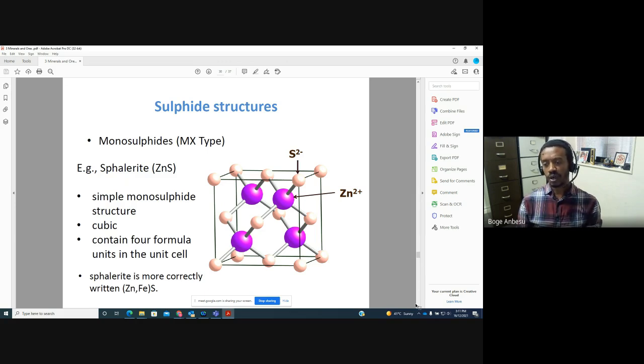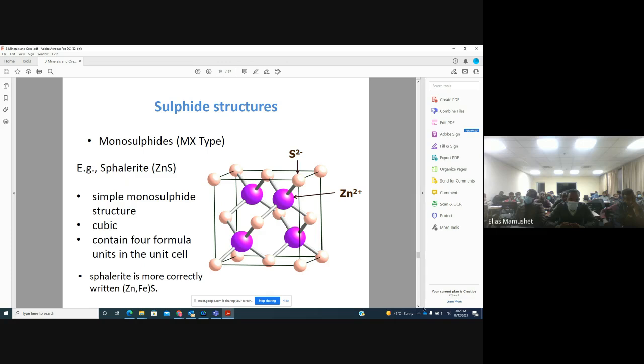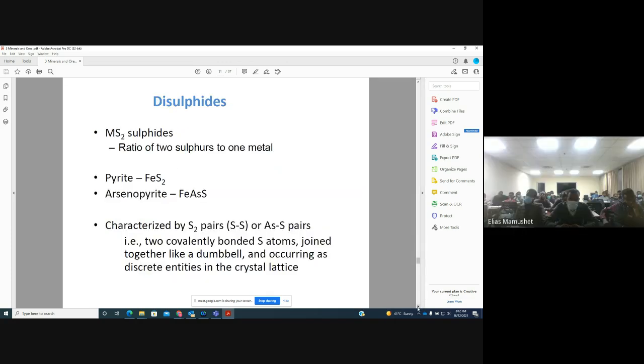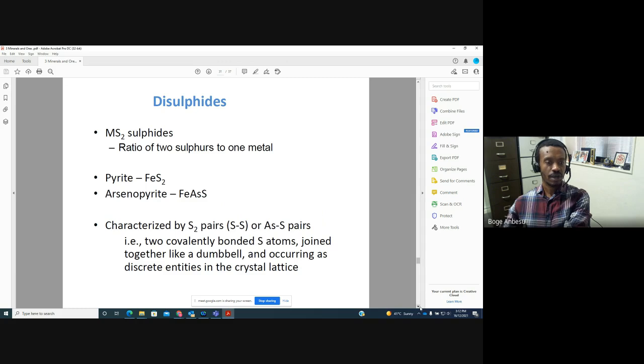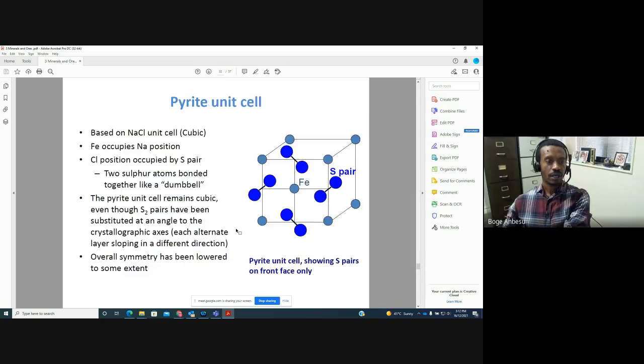Okay, so those purple atoms shown there in the crystal structure can be replaced by iron. And so in this case, you can talk about a variety of sphalerites. Some of them have a small amount of iron in them. Some of them have lots of iron in them. So again, the value of the sphalerite can depend on how much iron you have in the mineral. So we'll talk about solid solutions later on, but this is one example of solid solutions. So I mentioned disulfides such as pyrite and arsenopyrite. Again, instead of an atom of sulfur there, typically in the structure you have sulfur-sulfur pairs making up the crystal structure.